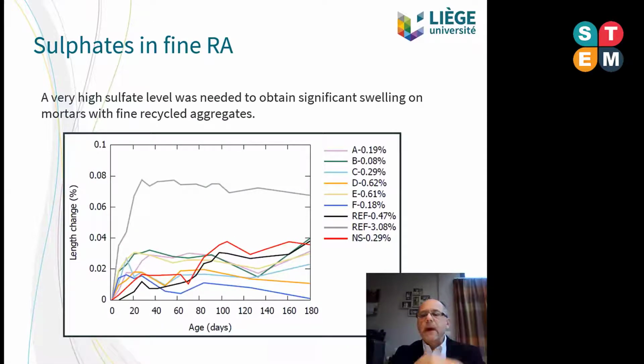We tried to study by recomposing materials in the lab, to define clearly the effect of the presence of this sulfate with the fine recycled aggregates that were used to produce mortar. And we measured the length change with the time of these different types of material. The observation was that we needed a high level of content, here the reference with more than 3%, to obtain and to observe really length change, which is corresponding to internal pressure and cracking of the material.